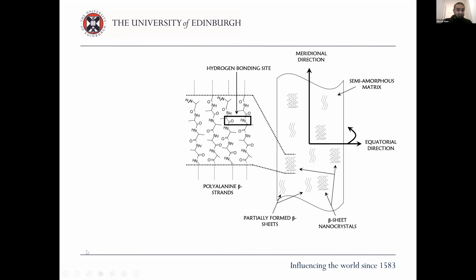Well, one of the reasons that they're so tough is basically that they are nanocomposites, and they have these polyalanine segments. During the spinning process, the spider will spin, and then it'll basically extrude this silk from its spinnerets. And the rate of extrusion will align the molecules, and through molecular alignment, you'll have polyalanine segments lining up and creating huge numbers of hydrogen bonds, which then end up resisting shear and storing energy within the nanocrystal.